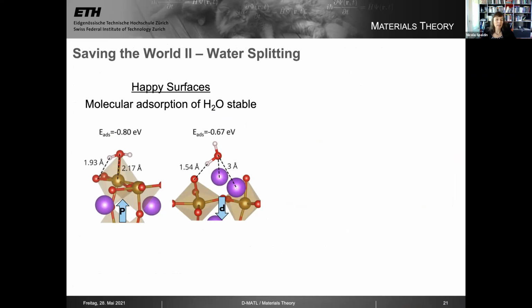Okay, so water splitting. Remember, we have two kinds of surfaces now. We have happy surfaces, which are charge neutral, and unhappy surfaces, which are extremely highly charged. And what we found, again, with our electronic structure calculations, is that on the happy surfaces, water molecules like to adsorb. They adsorb stably onto the happy surfaces, which is what you would expect, right? If you have a neutral surface, you're likely to be able to adsorb a neutral molecule.